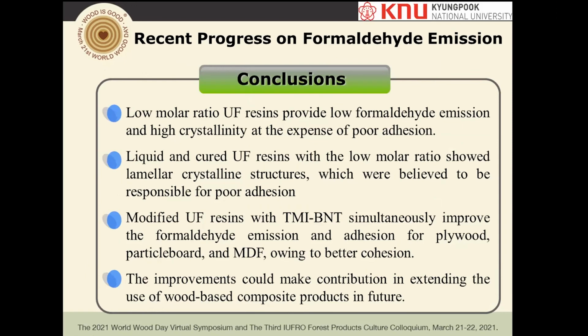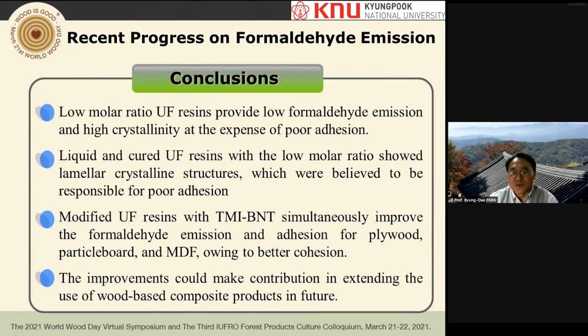So here's the conclusion of my presentation. I would say the low molarity resin gives low emission and high crystallinity at the expense of poor adhesion. The liquid and cured UF resin with low molarity shows lamellar crystal structures, which are believed to be responsible for the poor adhesion. The modified nanoclay simultaneously improves formaldehyde emission and adhesion in plywood, particle board, and MDF because of better cohesion compared to the control resin. These improvements could contribute to extending the use of wood-based composite products in the future, which may help in mitigating climate change.